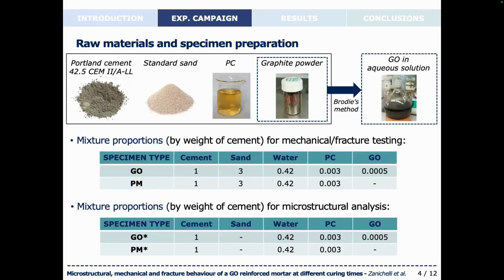Now, let me describe the experimental campaign we carried out at the testing laboratory of the University of Parma. In particular, the raw materials employed for the preparation of the GO-reinforced mortar specimens were the Portland cement, a standard silica sand, a polycarboxylate superplasticizer that is named PC, and the graphite powder. Then the GO in aqueous solution was obtained from the oxidation of the graphite powder by means of the Brodie's method. And then the mixture proportions employed to cast the GO-reinforced specimens are listed in the first line of the first table, here, by weight of cement.